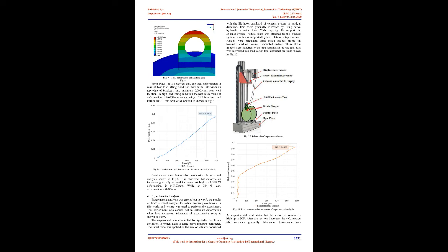The analysis results such as total deformation on exhaust system is given for maximum load value 588.2 N shown in Fig.5. Total deformation is 0.0959 mm maximum on the top edge of bracket and 0.0426 mm near weld location. It is observed that in most of the cases failure of bracket occurs near weld location due to varying loads. So, deformation is analyzed for various load cases.